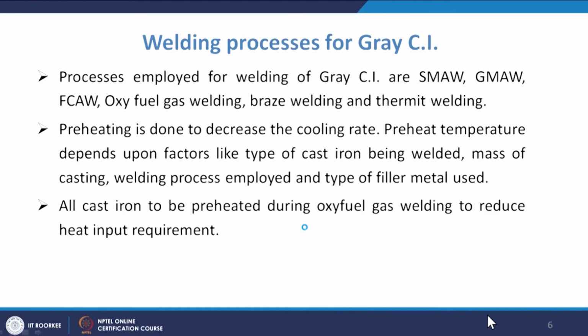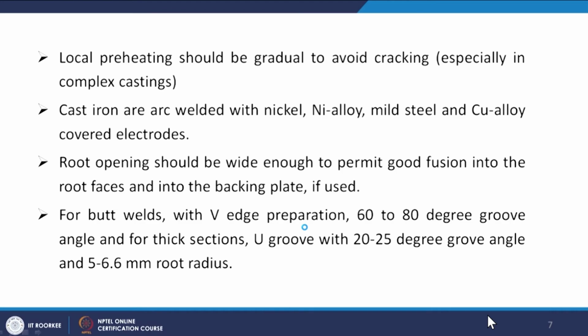Preheating is done to decrease the cooling rate, and preheat temperatures depend upon factors like the type of cast iron being welded, the mass of the casting, the welding process employed, and the type of filler metal used. All cast irons are to be preheated during oxy-fuel gas welding to reduce the heat input requirement. Local preheating should be gradual to avoid cracking, especially in complex casts.